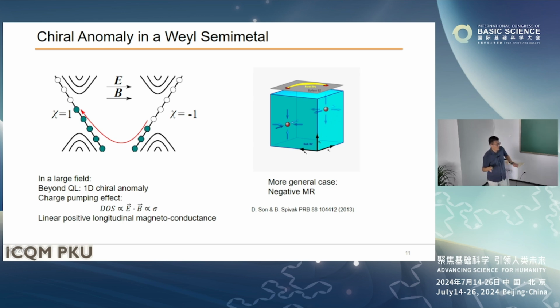in a high enough field, beyond the quantum limit in the last Landau level, because your density of states is proportional to B, and this gives a proportional conductivity, meaning you have a charge pumping effect. You apply more magnetic field, and your conductivity becomes higher. So you have negative magnetoresistance, and that is a chiral anomaly. Here, the magnetic field and the current direction are parallel. This is the high field limit, and even at a low enough magnetic field, some people also predict that you also have negative magnetoresistance.